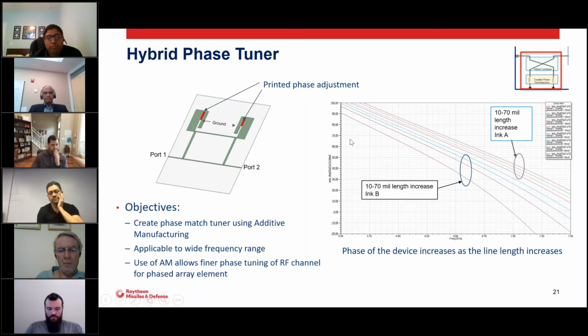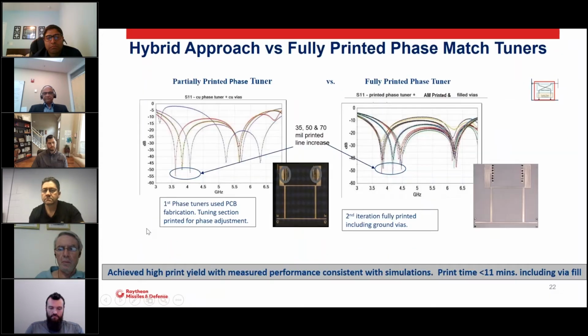We started with a laminate structure where we literally just had all of this on Rogers material with traditional printed circuit board, and we were just tuning the element by filling in where you see the red. This is a grounded line here, and we could do a phase adjustment by how much we filled this in. All right, so a very, very simple place to start. This was our result on our partially printed tuner. We were able to show that we could adjust phase based on the lengths we printed, but that was just our starting point.